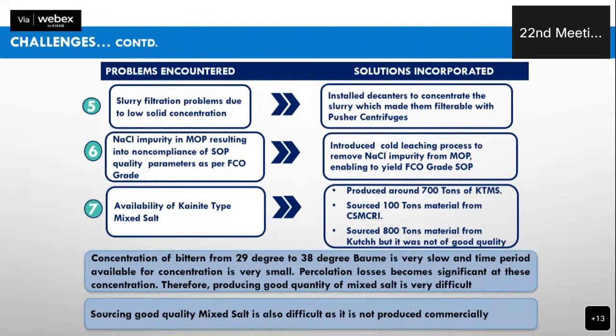Then availability of raw material, that is kainite type mixed salt, because as we discussed earlier, it is getting crystallized above 36 Baume. So time period available to produce kainite type mixed salt is very small, because once we start harvesting solar salt, then we generate bittern, which is of 29 Baume. So from 29 Baume to 36 or 38 Baume, time period available is not much, and it has to be done before monsoon. So we were able to produce around 700 tons of kainite type mixed salt.